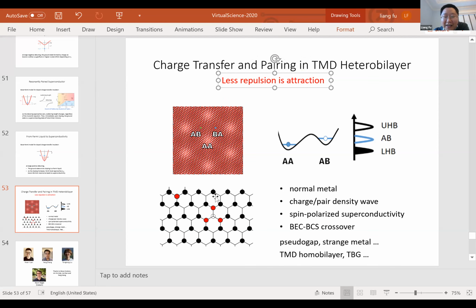Alternatively, if the kinetic energy of the holes is large, holes and trimers can coexist, and they can interact resonantly with each other to form superconductivity. Here the superconductivity appears even in the spin polarized regime. So the pairing mechanism is not based on the spin degree of freedom, but based on the charge.